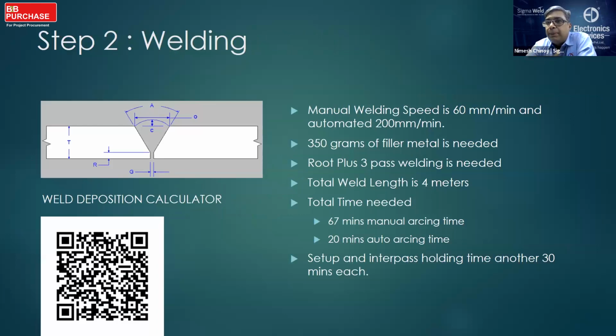Manual welding speeds are typically in the range of 60 to 200 millimeters a minute with a little bit of automation. The filler wire required to do this is close to about 350 grams per meter for an 8 mm thick plate. There's a small calculator. If you take out your phone and take a photo of this QR code, it will lead you to a form which will allow you to feed in the data, and it will calculate the weld deposit material required by you, and it will email it to you.